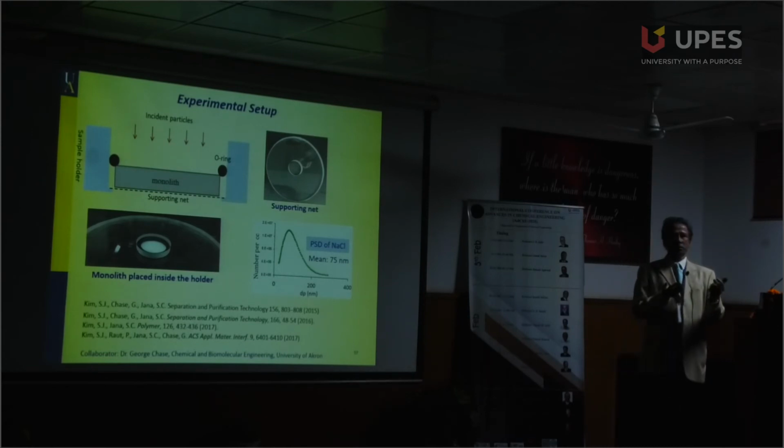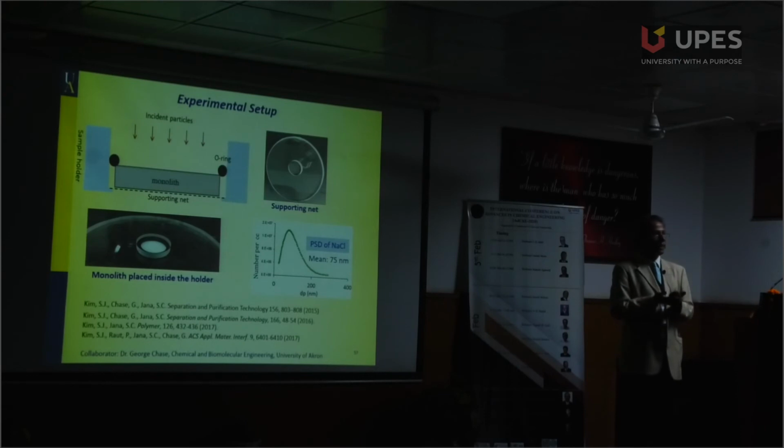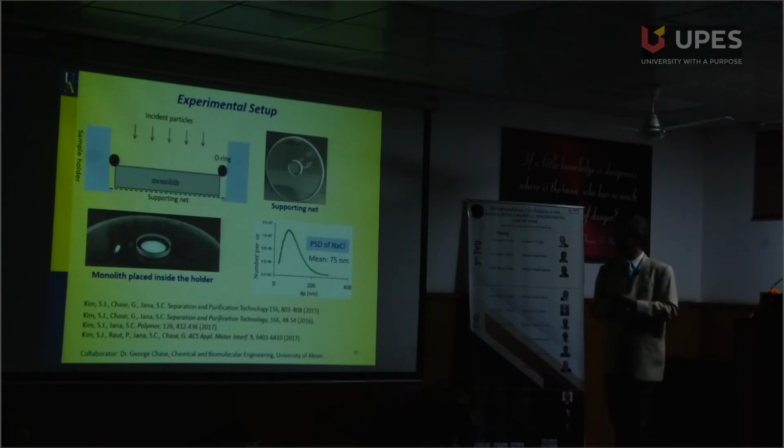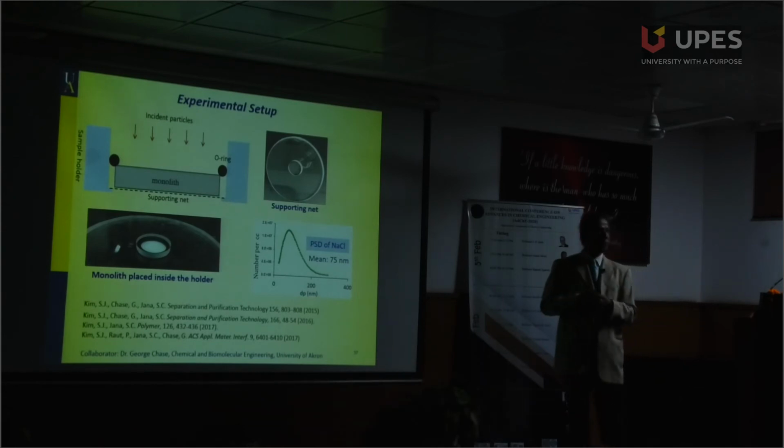You can also use Darcy's equation to find out the permeability. What we found is that commercial filters have a permeability of about 10 to the minus 12 meters squared, and our material gives us about 10 to the minus 10 meters squared. So it's about a factor of 100 higher rate than what you can get in a commercial filter, because it's 90+% porous.